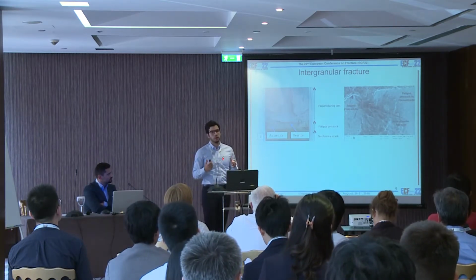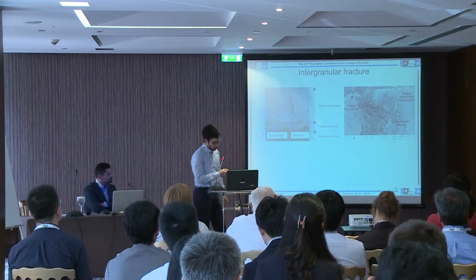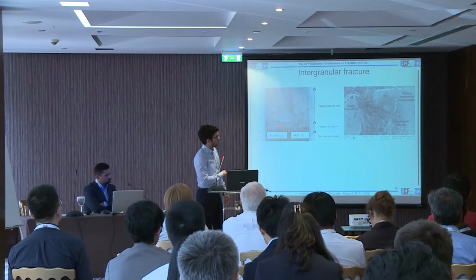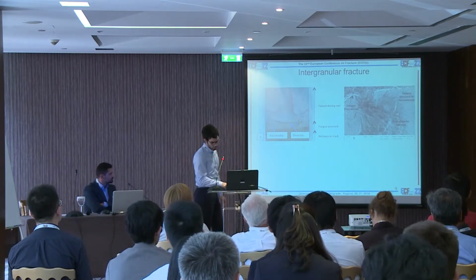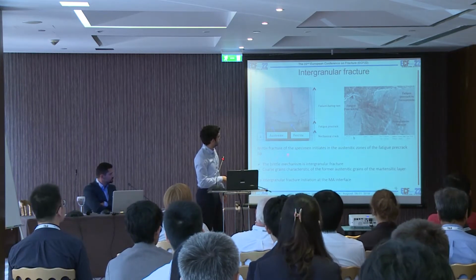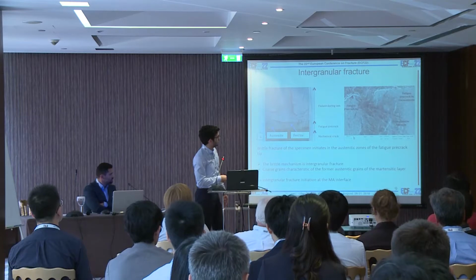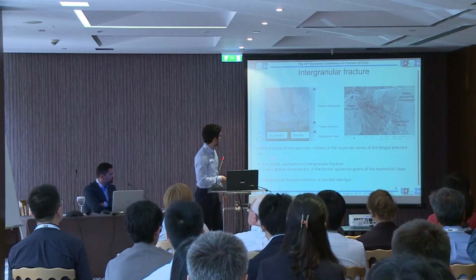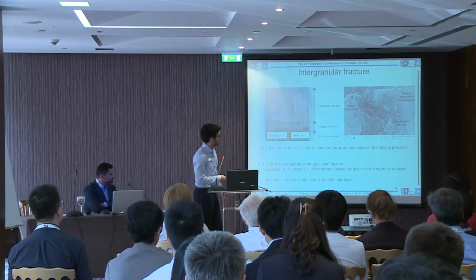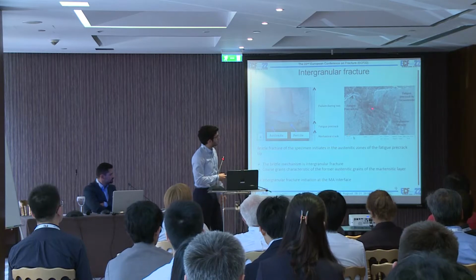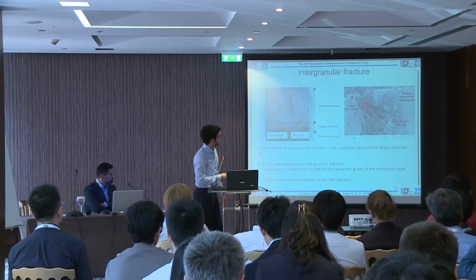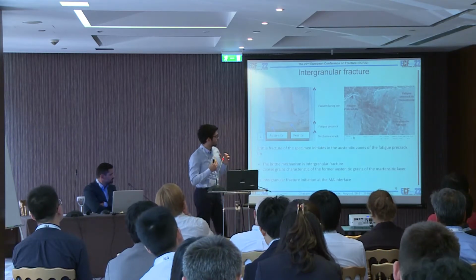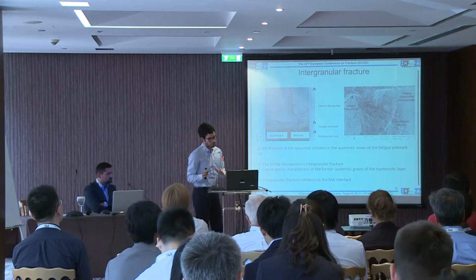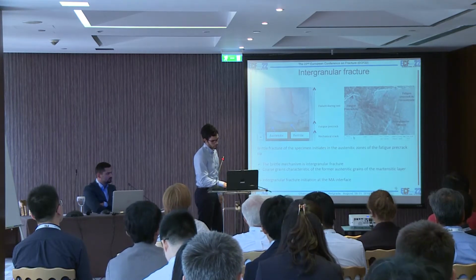SEM analysis is required to understand what role the austenite plays in the fatigue pre-crack. So we take a low toughness specimen and we analyze the austenitic parts of the fatigue pre-crack, which we see here, and we see that the failure of the specimen, as we expected, initiates in the austenitic zones of the fatigue pre-crack, and that the brittle mechanism which is involved is intergranular fracture, as we see here. And we can see the coarse grain boundaries in this fracture surface, which are characteristic of the former austenitic grains of the martensitic layer. So this brittle mechanism initiated at the MA interface.